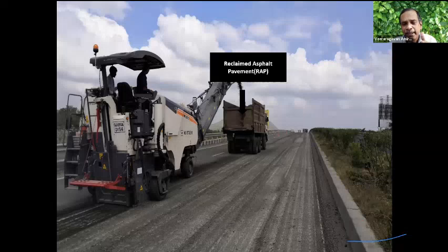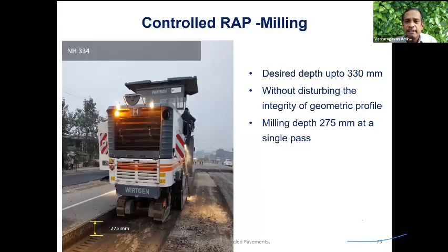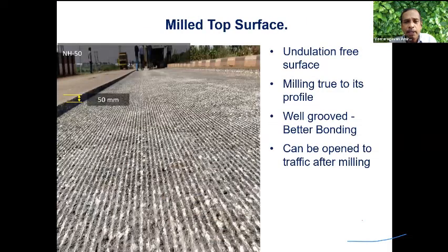So this milled material is taken to a central plant. You can reuse it either 100% in cold in-place recycling, or a higher or lower percentage in the case of hot in-place recycling. So if they say depth, this is how your surface will look. You'll have a better bonding, and no crack from the bottom layer will propagate to the top.